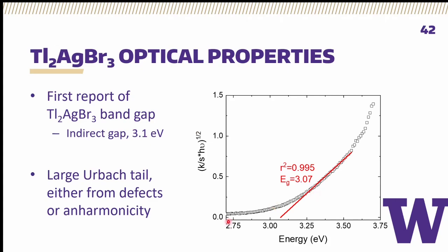There was a large Urbach tail in the system, which we attribute either to anti-site defects, as the sample was silver rich and thallium poor by EDS, or potentially anharmonicity in the band structure of thallium silver bromide. Again, it's not a very well studied system, and this is a common problem that creates these large sub-band gap absorption tails in high Z systems.